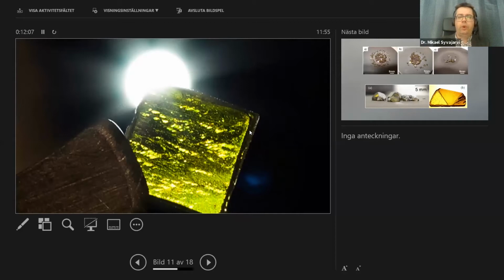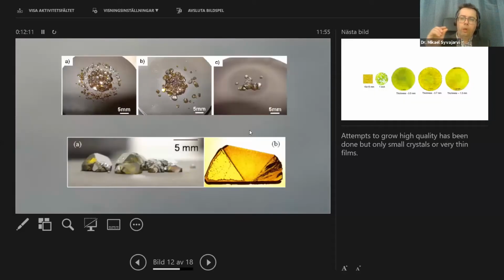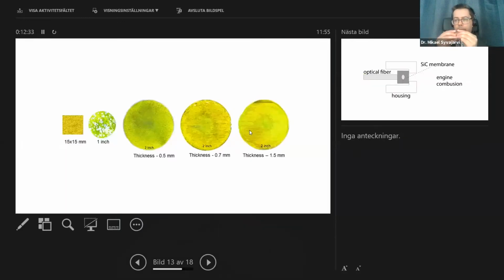During the years it has only been possible to grow very, very small pieces of cubic silicon carbide, to control the growth and so on. So many research groups have explored these things. But what we succeeded with was to control the growth in a little bit better way. So these small crystals became a little bit larger and larger over time. And then we started to have larger grains. And this also means that we have better quality of the material. So that's how we came into the cubic silicon carbide.